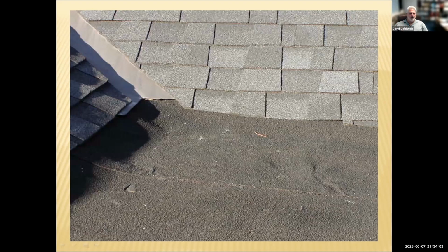Now, just to back up for a brief moment, anybody know with asphalt roofing, what is the lowest slope you're allowed to go? Anybody know? Sean, are we getting any answers to that? 3 in 12. Anybody want to guess again? 2 in 12. 2.5. 4 in 12. Okay, let's make a deal, right? The answer is you're allowed to go down as low as 2 in 12, provided that you have a double underlayment. Without a double underlayment, it's 4 in 12.